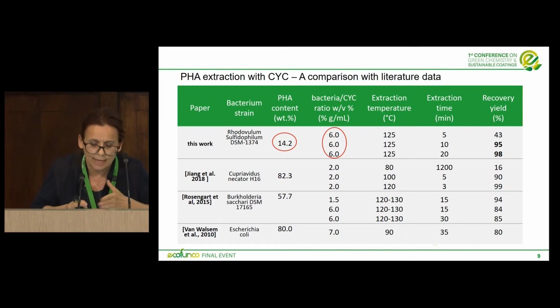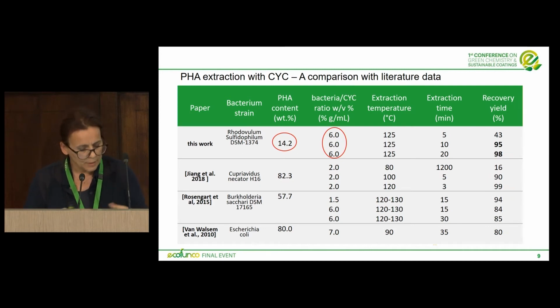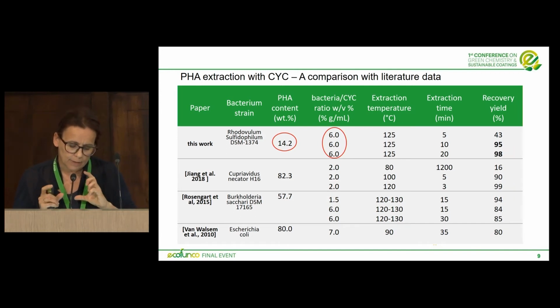So in this slide, you can see a comparison with literature data, and you can see that the results obtained are very good compared to the results obtained in other works where cyclohexanone is used to extract PHA from different bacteria. And you can see the very good results considering that in our work we have processed a biomass with a very, very low PHA content, 14.2%, compared to the higher PHA content in the biomass used in the other works. And in addition, we have used a lower ratio of solvent to biomass in this work compared to the other works.